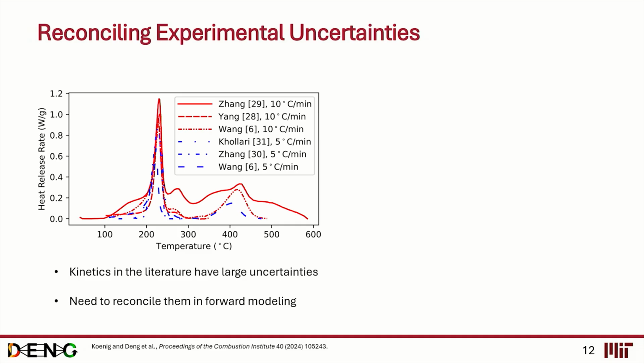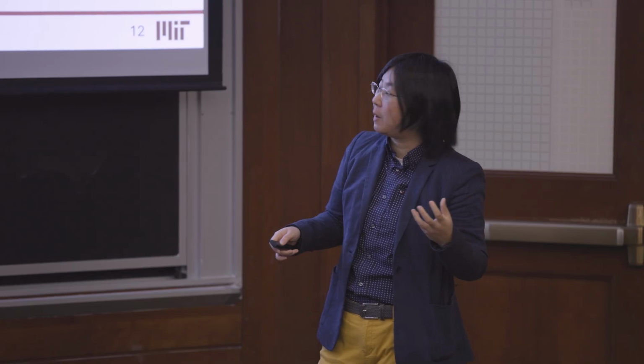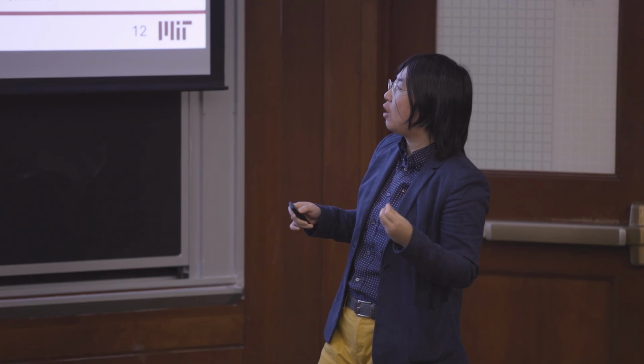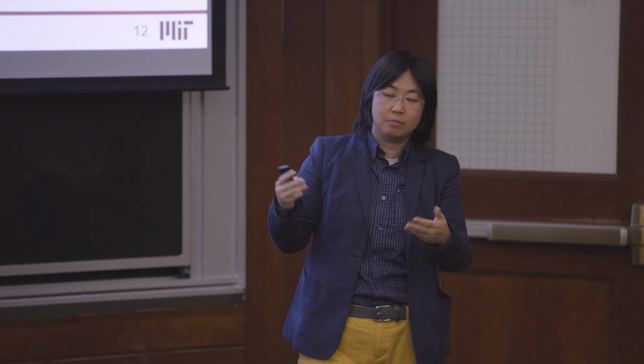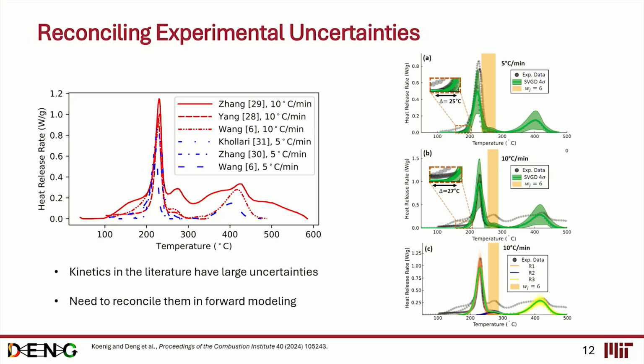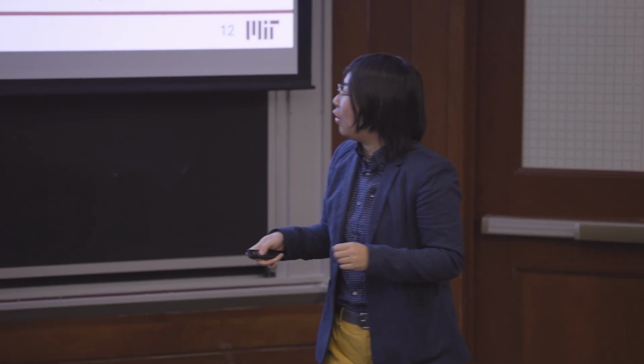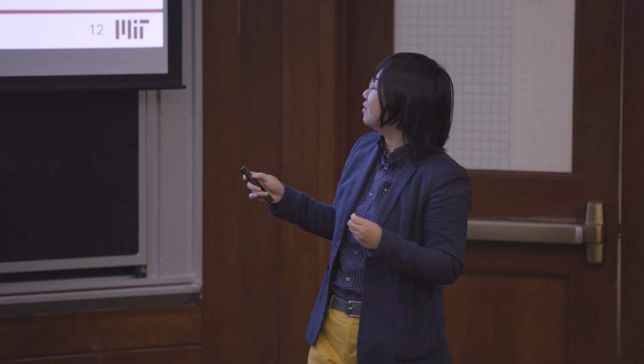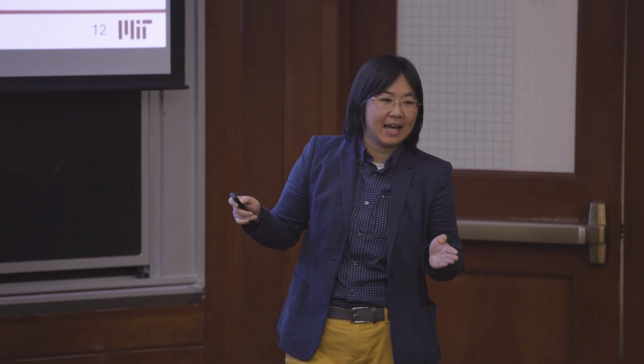That actually showed that the experimental data itself is highly uncertain, with experimental errors and uncertainties. So our model needs to be able to accommodate a wide variation in all the data. We presume they are true, but they have uncertainties. So we developed a further module to model the uncertainties in the experimental data, such that our model is able to capture the uncertainties and give us an ensemble prediction of all the possible scenarios, taking into consideration the variations in the chemical kinetic parameters.